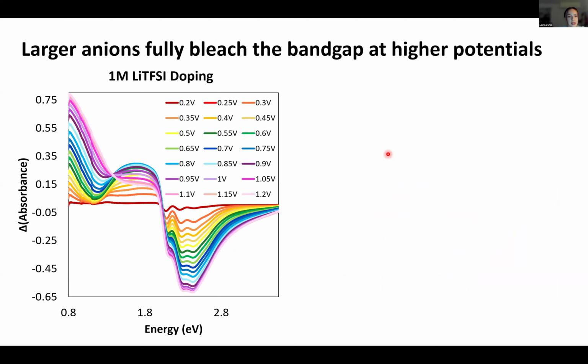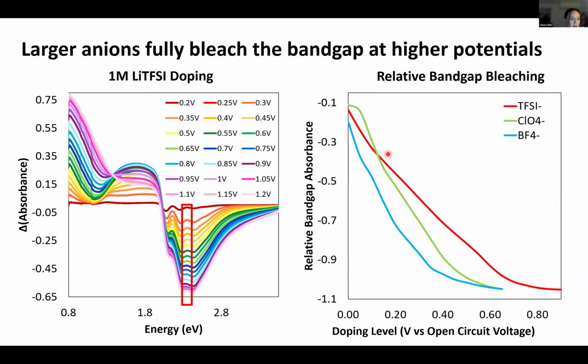So if we're just looking at the band gap bleach, we can zoom in on this potential right here and plot the absorbances for each salt as a function of the doping level for each salt. So here's what we get when we do that. And we see that the smaller anions, which are the blue and green, are bleaching the band gap at lower potentials compared to our largest anion.